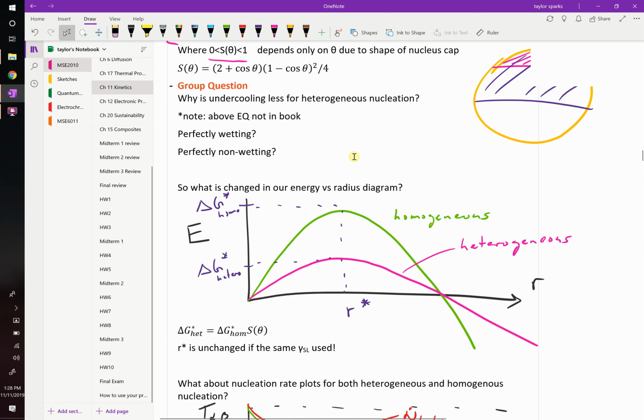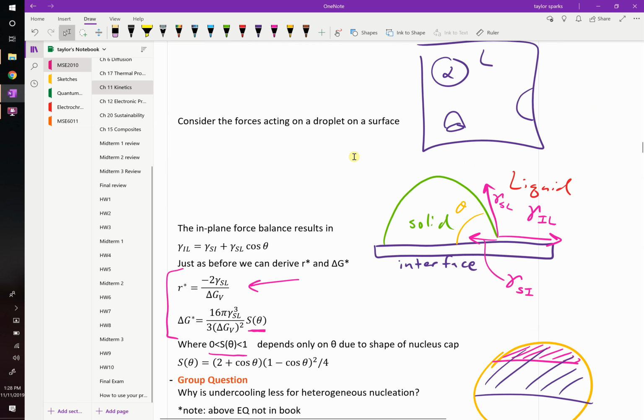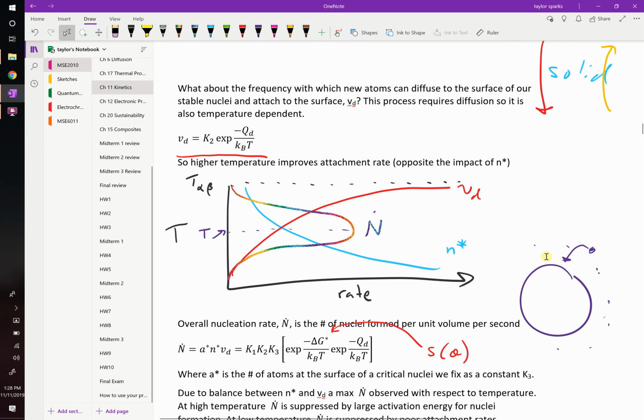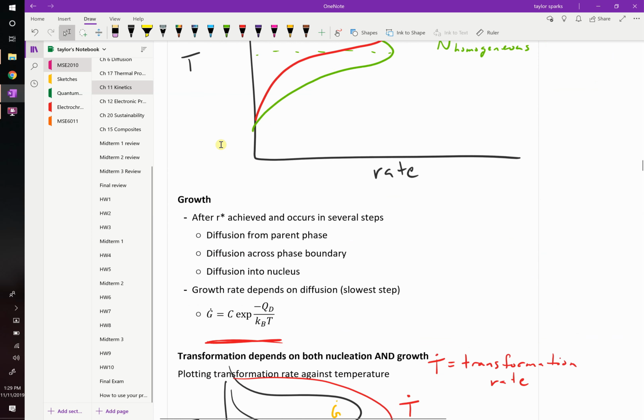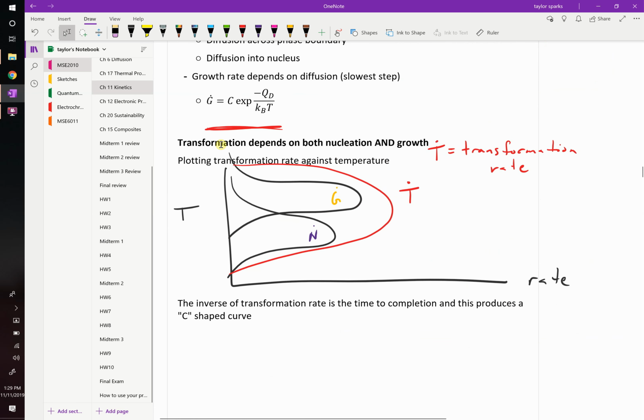Okay, so we're not going to get way into it in this class, but the main idea is this: this is where we derived V sub D, the attachment rate. It basically had to do with the rate at which particles near that thing can diffuse and attach themselves. Whereas growth is slightly different kinetics because remember from two chapters ago we talked about grains growing? We showed you how the small ones shrink and the big ones get bigger. Those are slightly different kinetics because it's all in the solid phase now and yet they're growing. We're going to model them as both having their dependences on the diffusion activation energy, but they'd have different constants, K2 versus down here we called it just C. But very similar kinetics, okay?